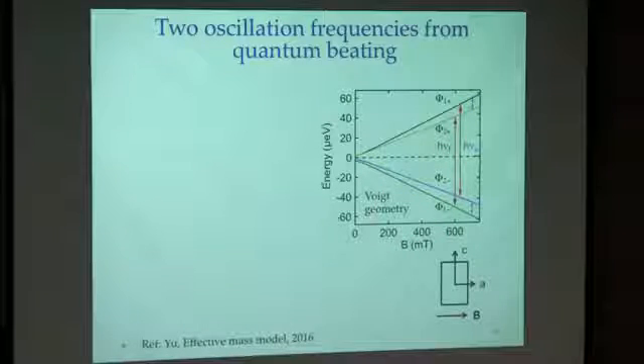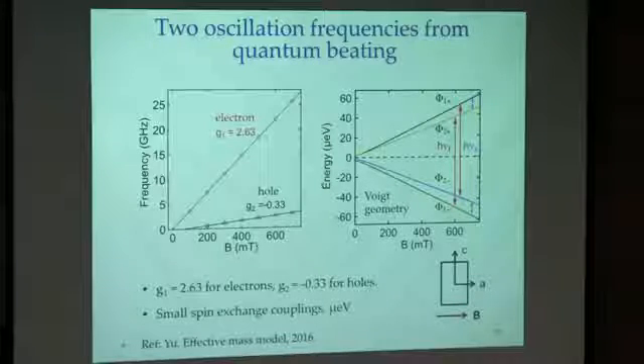And in the case of a small spin exchange coupling, those 2 differences are very close to each other, and the other 2 are also very close, so the 4 frequencies reduce down to 2. And we thought that's what's going on in our measurement. We have 2 frequencies there.